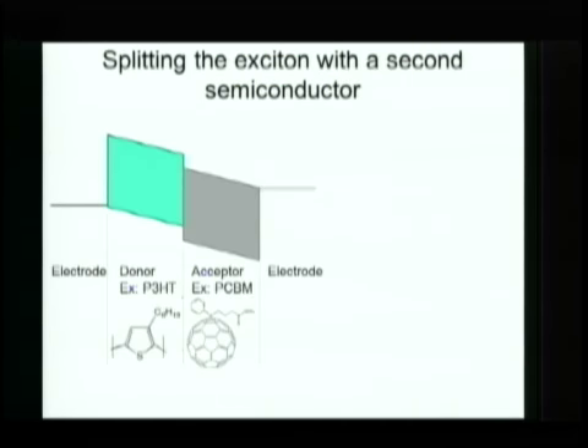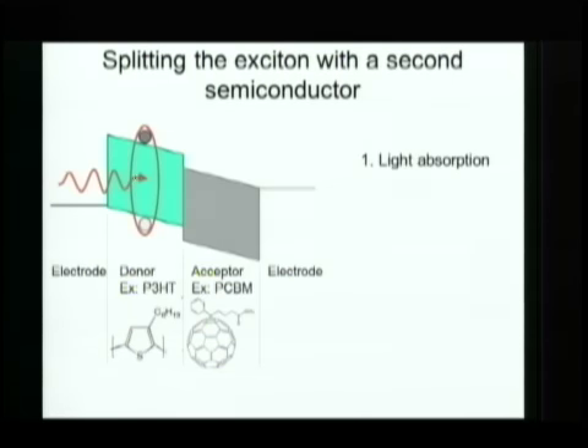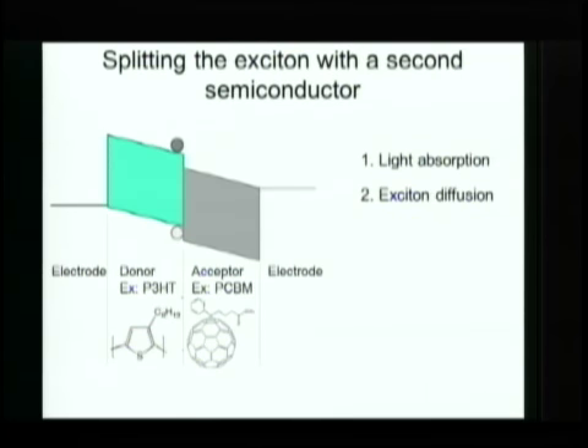And Ching Tang did it when he was working at Kodak. He realized that there needed to be a second semiconductor, and this is where the donor and the acceptor come in. And so if you have a layer of donor and a layer of acceptor, light will come in, it'll be absorbed, and it will form an exciton. And then that exciton will travel or diffuse to the interface between the semiconductors.